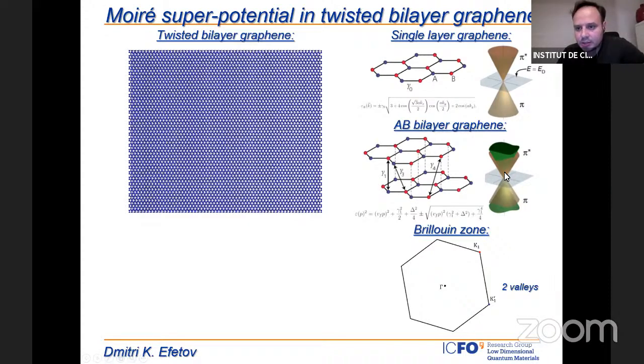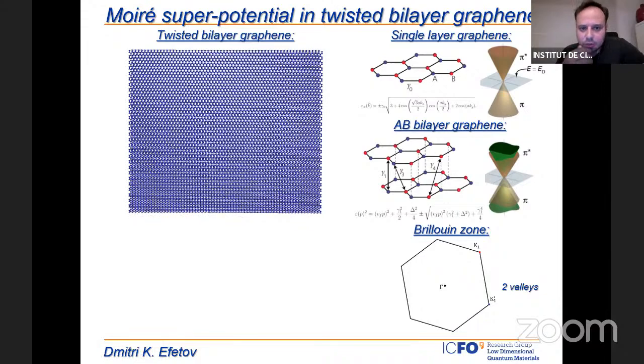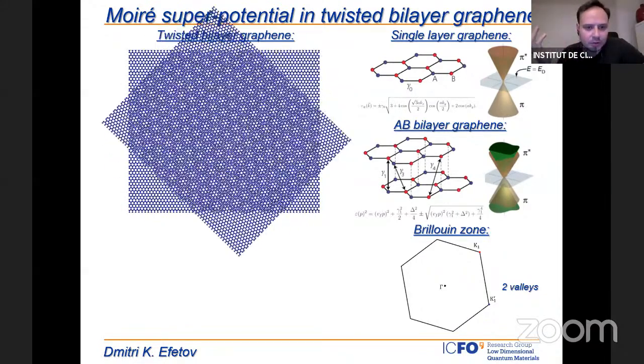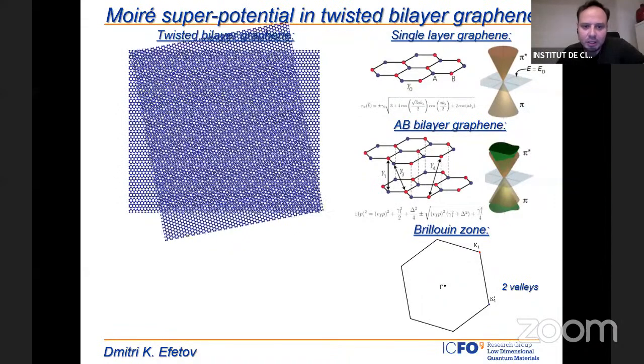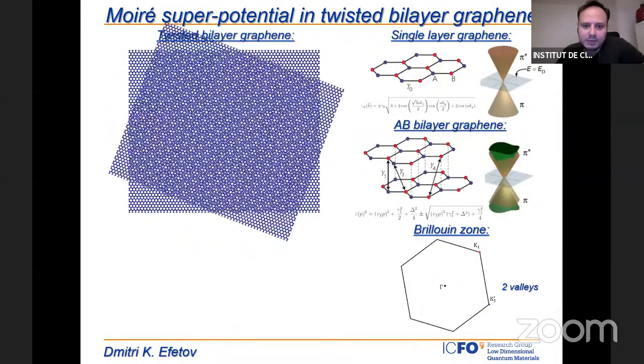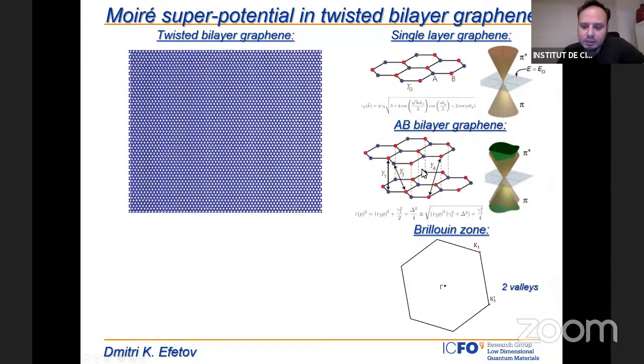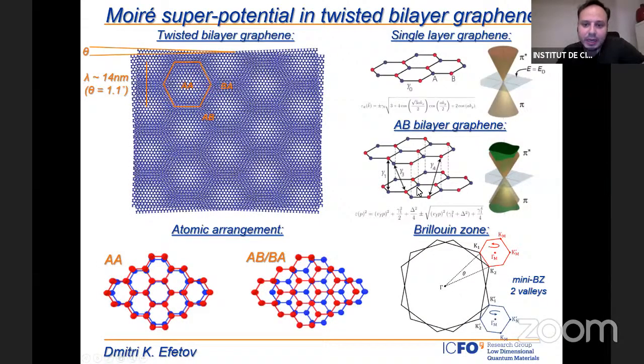And what I also want to mention, I have shown here only 1 valley, but in general, graphene has 2 valleys in the K and K prime points. And basically, in addition to spin, we have another degree of freedom, which is valley. So graphene is 4-fold degenerate. And so, what happens if we now do the trick and we now just randomly twist one layer on top of another? As you can see, this explanation which I gave you for AB bilayer graphene completely stops working, because now all these hopping terms between the top and bottom layer are basically screwed up. They basically oscillate with this superlattice which is formed, right?